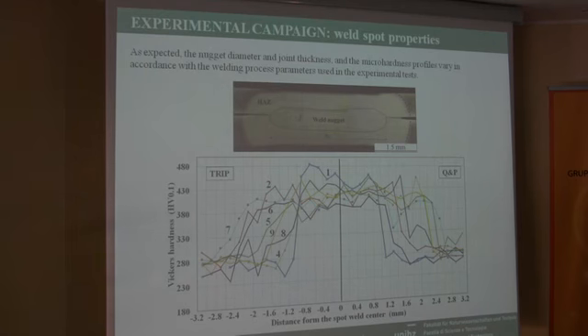In particular, here you can see the microhardness profiles obtained in the joints in the several welding conditions, but you can have a look in the manuscript. Generally, we have an increase of hardness in the weld nugget because we have a formation of full martensite within the nugget, and then we have a reduction of the hardness coming from this region to the base material. Considering that in this region we have some tempering phenomenon of the bainite in the TRIP steel or the martensite in the quenching and partitioning steel.